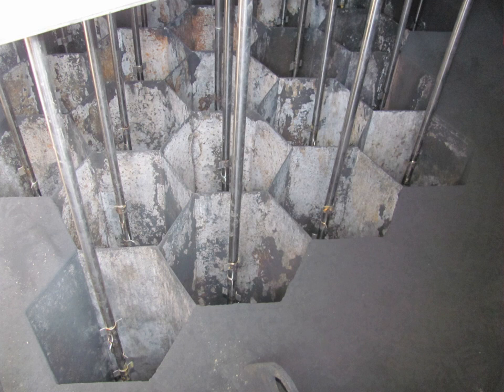In low-resistance dust layers, the corona current is readily passed to the grounded collection electrode. Therefore, a relatively weak electric field, of several thousand volts, is maintained across the dust layer. Collected dust particles with low resistance do not adhere strongly enough to the collection plate. They are easily dislodged and become reentrained in the gas stream.